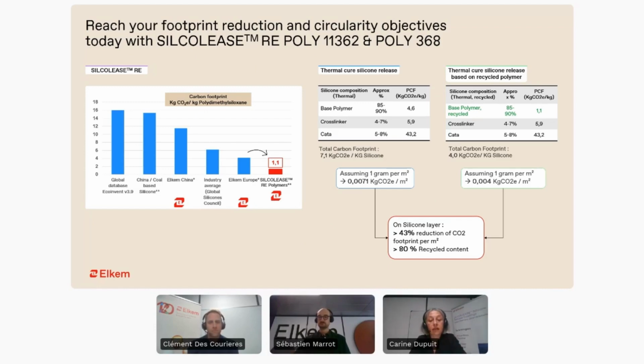These two new grades are significantly contributing to emission reduction by drastically reducing the carbon footprint to 1.1 kilograms CO2 equivalent per kilogram, which represents a reduction of more or less 70% compared to the virgin counterparts. When mixed with crosslinker and platinum catalyst, the positive impact is a little bit reduced, due to the fact that the crosslinker and the catalyst have a higher carbon footprint.